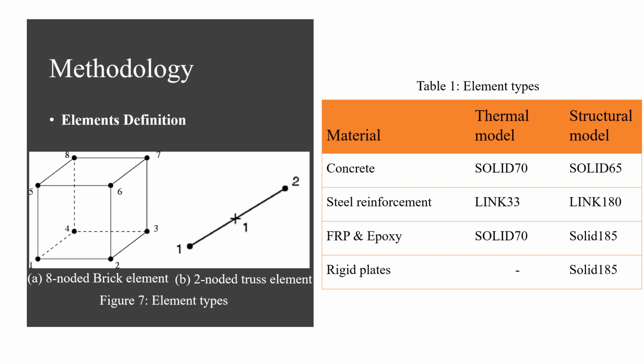Also, steel reinforcement was modeled using a 2-noded truss element. FRP and epoxy were just like concrete, Solid 70. Now for the structural model in which stresses and displacements are found, equivalent element types were used. So for concrete, Solid 65 was used, and this element is capable of simulating concrete cracking and crushing. However, FRP, epoxy, and the rigid plates were simulated using the linear brick element Solid 185, which doesn't have the ability of cracking and crushing.